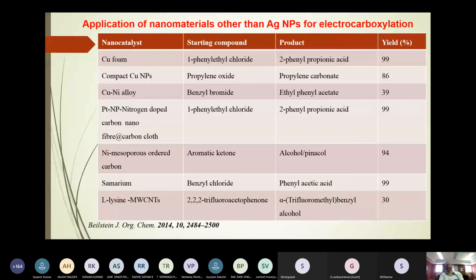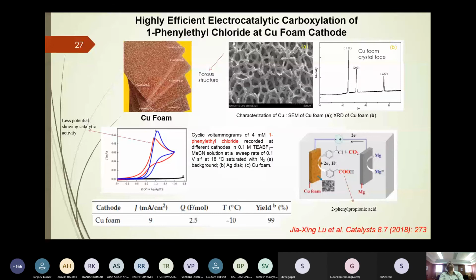Moving to the second part, where we see non-silver based nanoparticles for carboxylation, for example copper nickel alloy nanoparticles, nickel, and carbon materials without metals. This slide shows the carboxylation of 1-phenylethyl chloride at a copper foam electrode, where we can see the porous structure of the copper foam nanoparticles. XRD confirms the presence of copper nanomaterials.